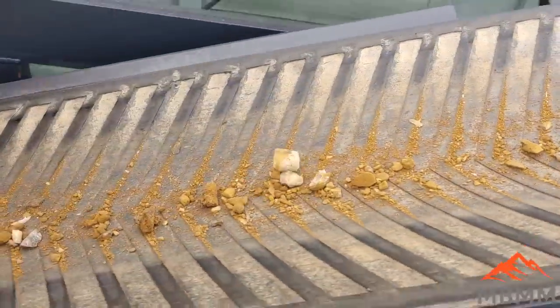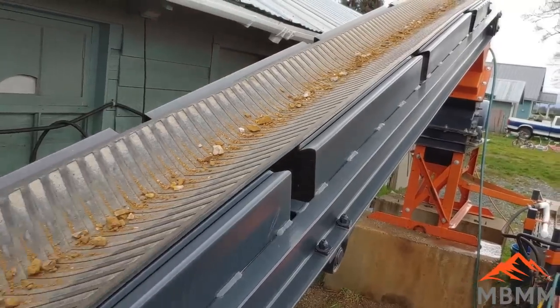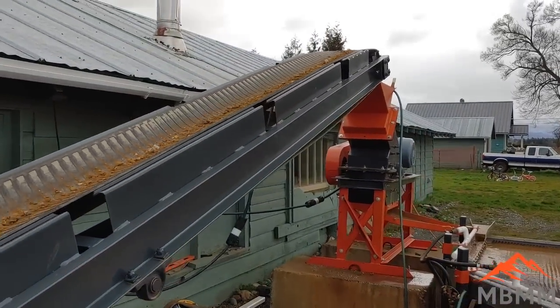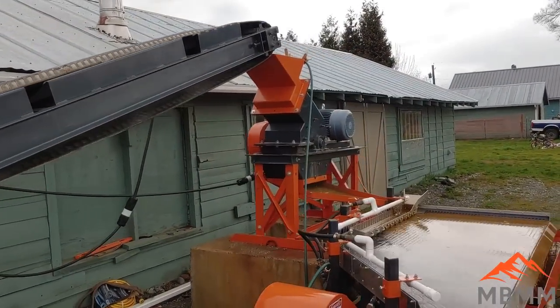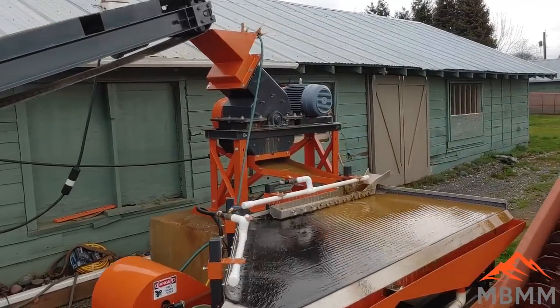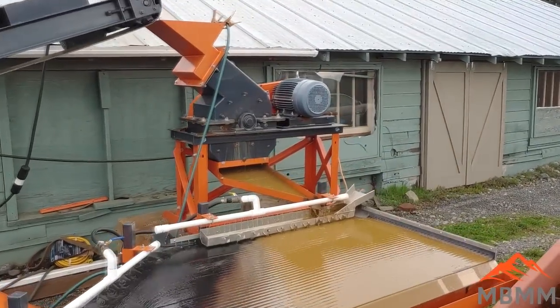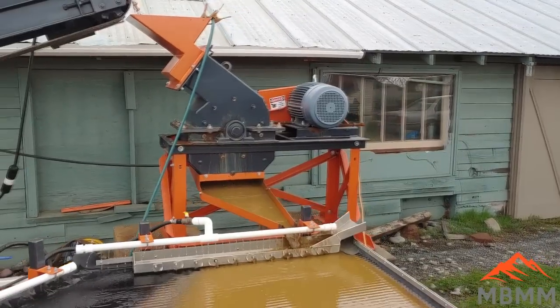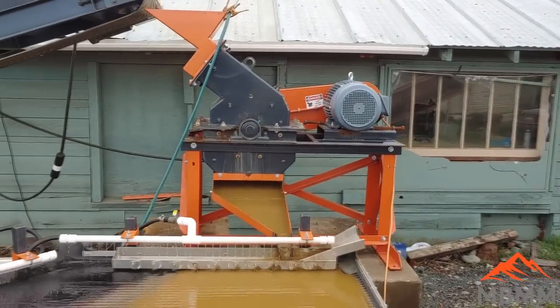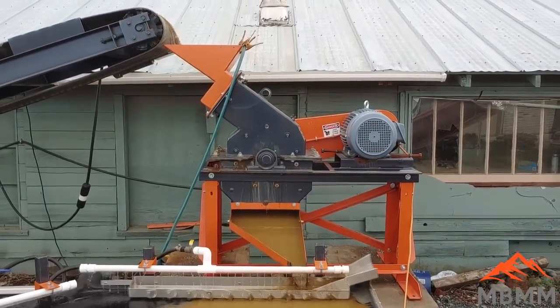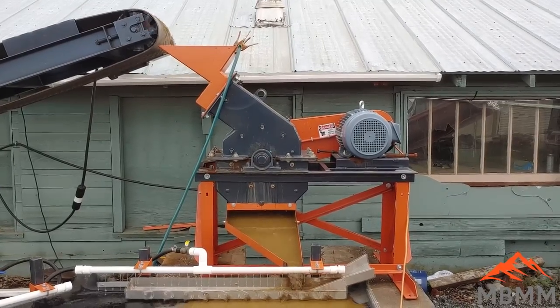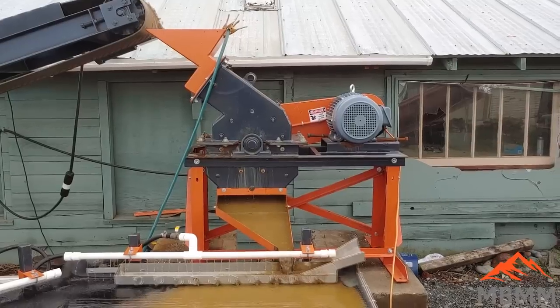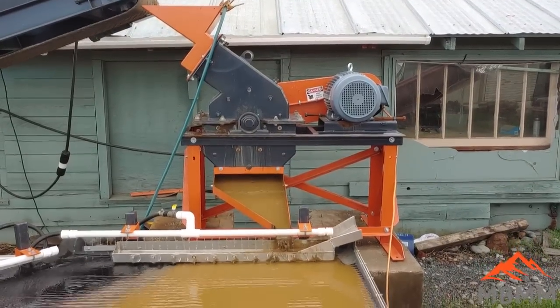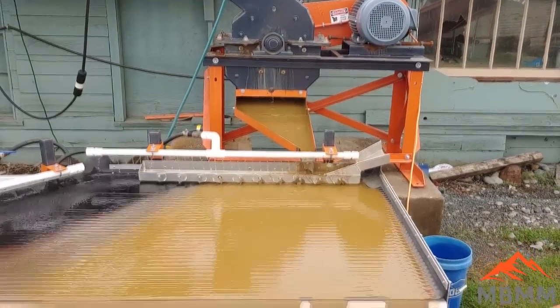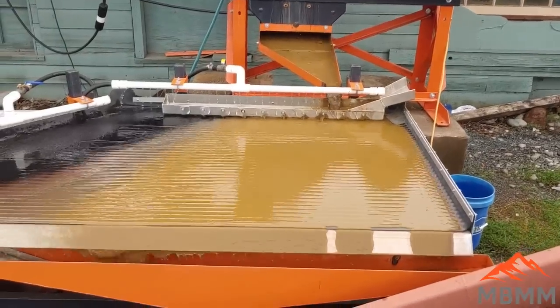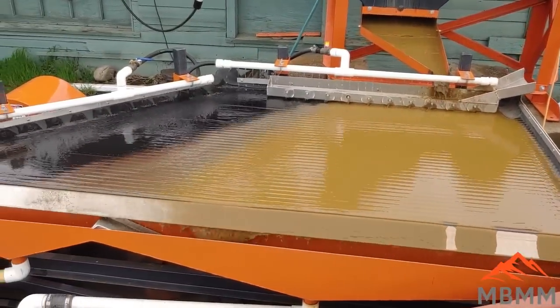Out onto this conveyor, which goes up into our 16-inch by 12-inch hammer mill. This hammer mill has a 0.8 millimeter screen in it, and with that size screen, the crush size is about 70% passing a 30 mesh and 50% passing a 50 mesh screen. In the hammer mill, we have 20 high chrome iron hammers, which are very abrasion resistant, and they spin around at about 1200 RPM and crush the material. You add about 1 gallon or 2 of water per minute to help flush the system. It makes a really nice wet slurry that comes down this chute and runs right onto our 4x8 shaker table.